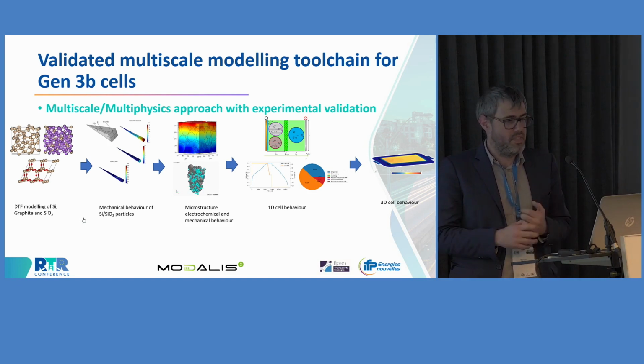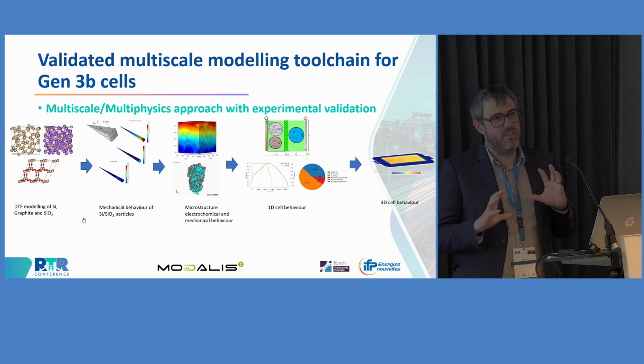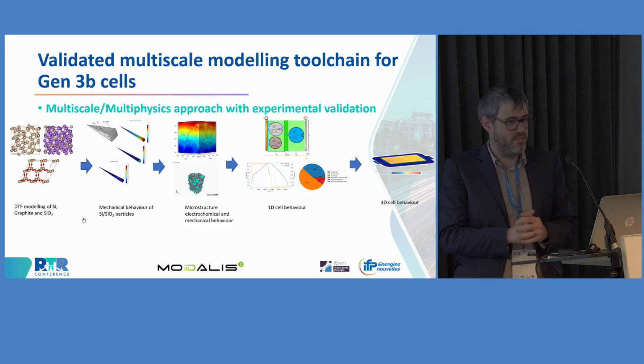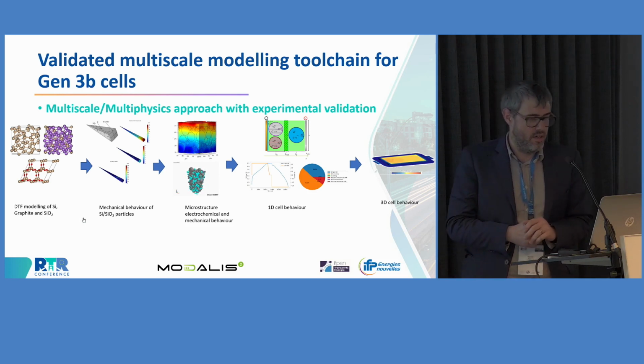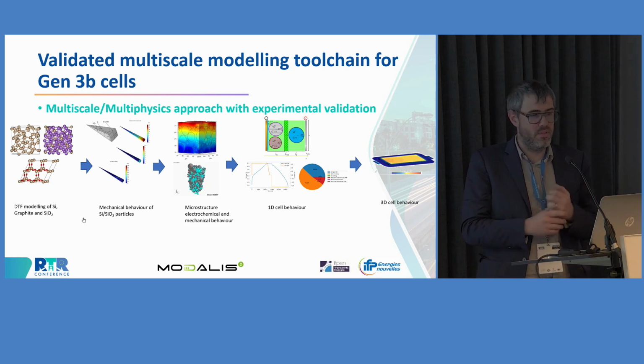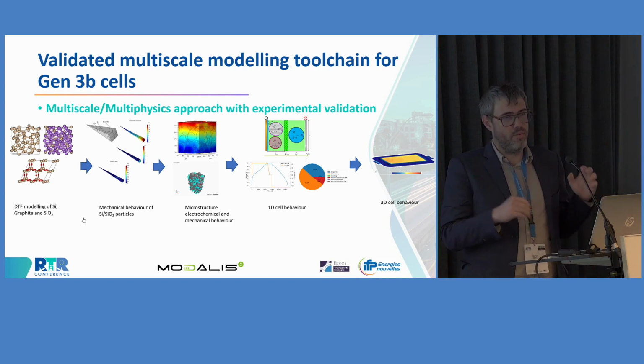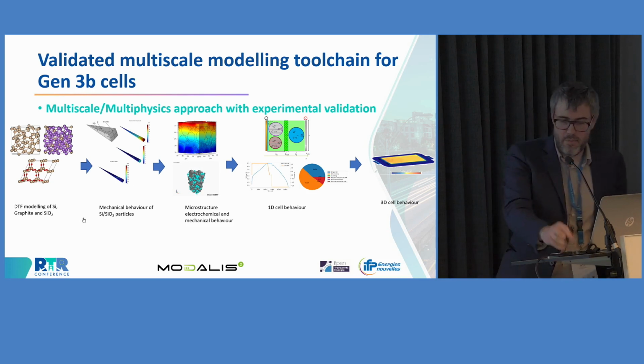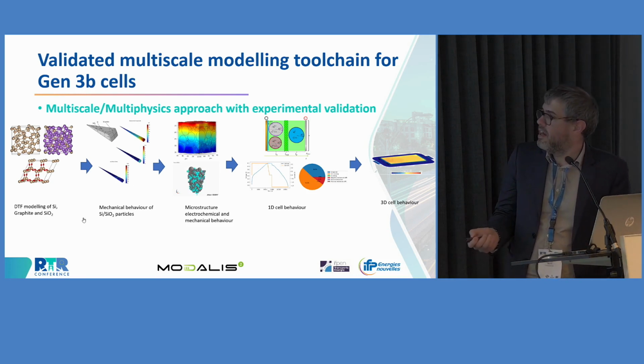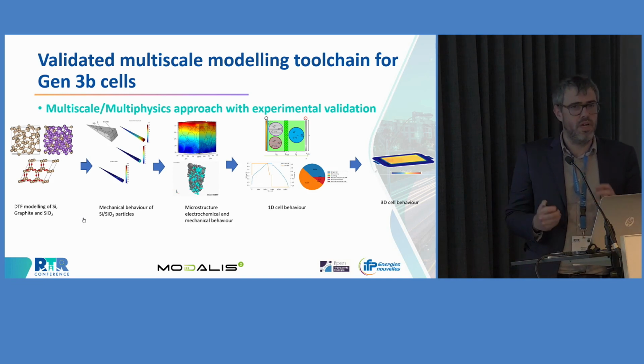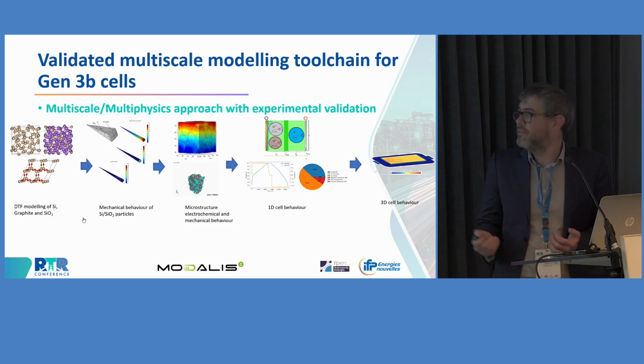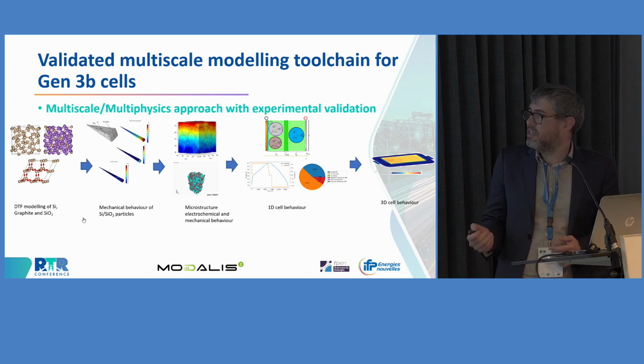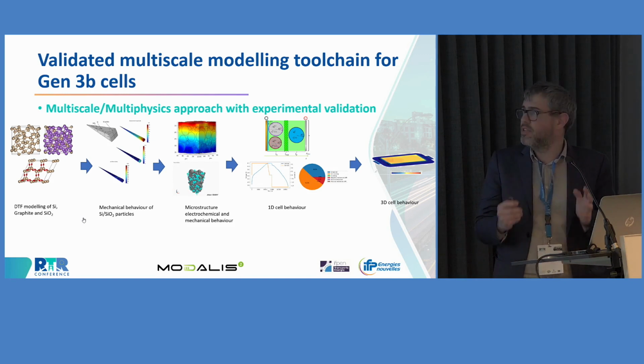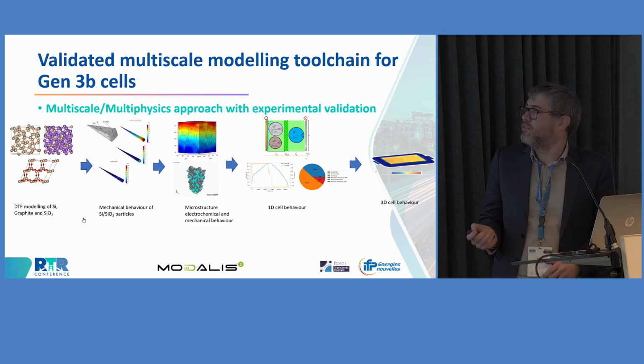So this is very specific to our application because we have very specific particles, especially for the negative electrode, with inclusion of silicon into a silica matrix, and this led to a specific behavior of the particles that needed to be taken into account. These particles, once they were modeled, were put into an electrode scale modeling, where we were able to study the mechanical behavior of the electrode. Then this gave us some information on how the electrode works in order to implement it into a full 1D cell